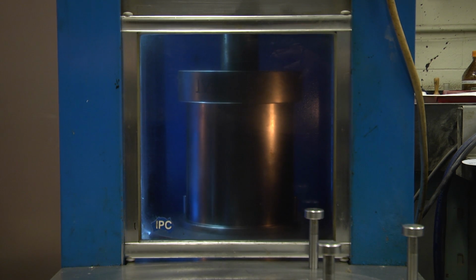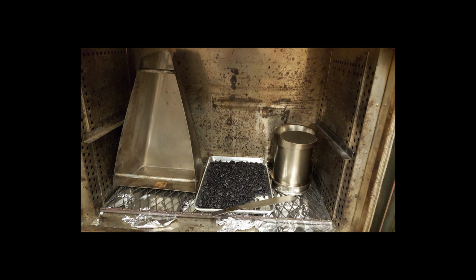revolutions per minute. The following summarizes the steps required to complete Superpave Gyratory compaction of previously prepared loose asphalt concrete mixture. Preparation of loose mixture is covered in a separate video. Place previously prepared loose mixture in an oven for short-term aging. The required amount of material for each gyratory compacted specimen is a function of the target specimen height and GMM. For 115 millimeter tall specimens used in mixture design, generally between 4,500 and 4,700 grams of loose mix is used for each compacted specimen. The loose mix is conditioned for 2 hours at the compaction temperature for short-term aging.